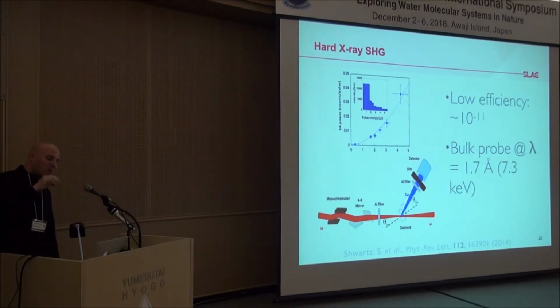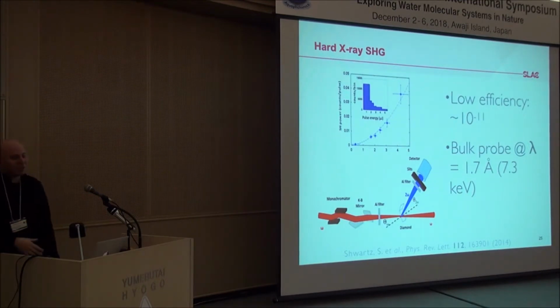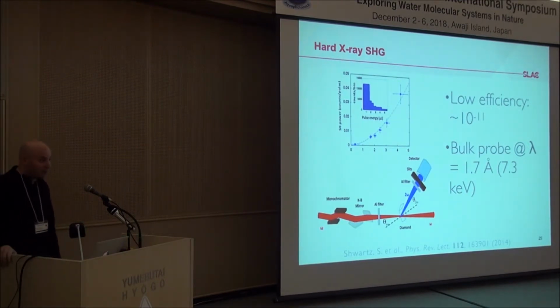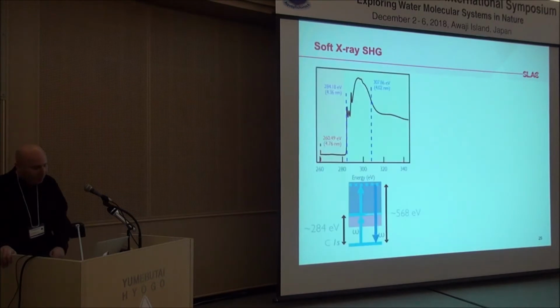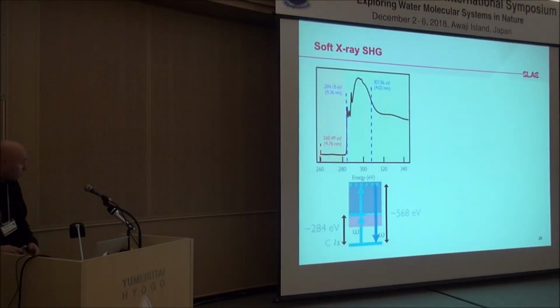And that's because there's a certain energy that it takes to bind an electron to a proton. And at these sorts of efficiencies, the fields required are above that, and you will inevitably damage every sample you take. So it is a massively expensive and difficult experiment. But we wanted to get around that. So we wanted to do soft X-rays, and soft X-rays had a lot of advantages.